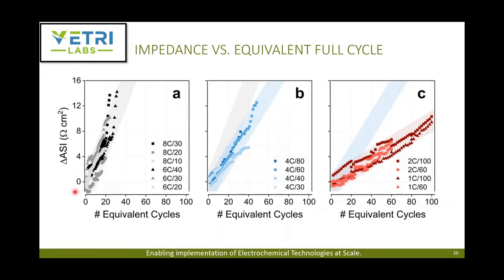here's the impedance rise with high rate, 8C and 6C. And when you come to 4C, here's the performance. And the 1C and 2C is here. As you can clearly see, there seem to be three regimes, strictly dependent on the actual charge rate and not necessarily where you're cutting off the state of charge. And the key takeaway, which is summarized in a later section, is that the state of charge is actually not preventing you from the impedance rise.